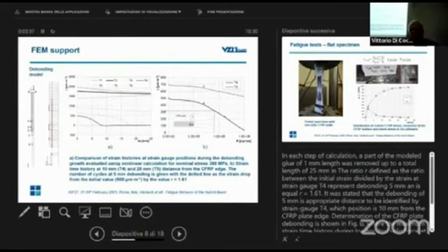During fatigue test, we observed the debonding of the CFRP plate, especially with strain gauges, and according to FEM support, it was calculated that when we measure strains at 5 millimeters and 10 millimeters from the edge of the CFRP, then when the strain decreased by the factor 1.61, the CFRP plate is debonded to 5 millimeters, and this is our criterion for then evaluating this SN curve, that 5 millimeter is sufficient debonding for the structure.